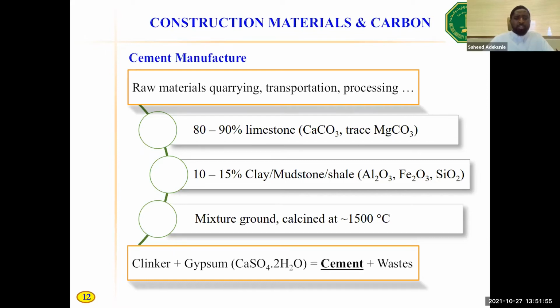Now, what is more important to note on this slide is the extremely high temperature of cement manufacture. This high temperature shows that a lot of energy goes into cement manufacture. And if you now add to this the energy to raise this high temperature, add to it the energy consumed in quarrying of the raw material, add this to the energy consumed in transportation, you will realize that the manufacture of cement is energy intensive. And in most places today, this energy comes from fossil fuels. And that means the cement manufacture itself is a major source of carbon emission into the atmosphere.